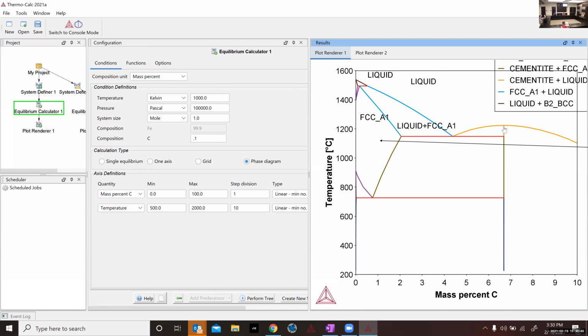This is called a congruent melting material. So when a non-single component phase, like cementite, comes up to a single point and melts, that's called congruent melting. So if you had a liquid with the composition 25 atomic percent carbon or 6.7 weight percent carbon, and you cooled that down under equilibrium conditions, it would congruently melt at a single temperature, somewhere around 1200 degrees. I think it's like 1273.